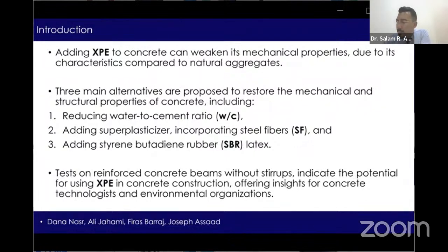Previous research studies showed that adding XPE to concrete can weaken the concrete mechanical properties due to its relatively reduced density, weak characteristic strength when compared to natural aggregates, and poor adhesion bond with the cement paste. Three main alternatives are assessed in this work to restore the concrete mechanical and structural properties after the incorporation of 3% XPE plastic waste. One, reducing the water to cement ratio from 0.55 to 0.46. Two, the addition of 1% steel fiber. And three, an addition of 15% styrene butadiene rubber, SBR, latex as a mixing water replacement.